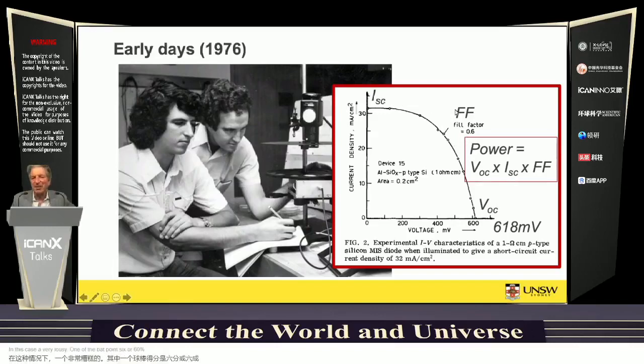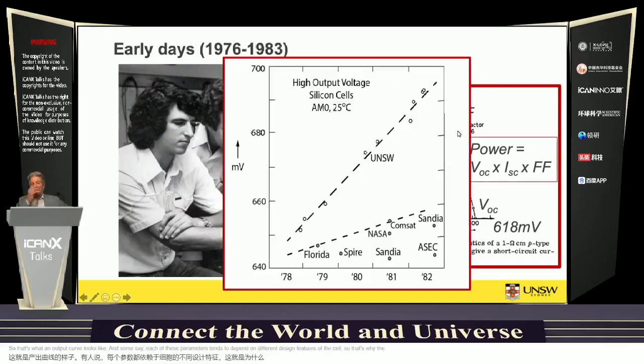But if you can get this curve squarer, you might get a better fill factor. It's possible to get them over 0.9 in some materials, but 0.8 is very good for a silicon cell rather than the 0.6 showing here. So that's what an output curve looks like, and each of these parameters tends to depend on different design features of the cell. So that's why the output's characterized in this way.